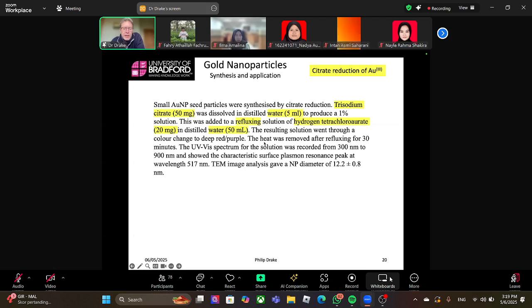You keep refluxing it. You then look at the UV vis spectrum, record from 300 to 900 nanometers, and you should see the surface plasmon resonance peak, 517. We're going to come back to the SPR peak later. It's a very important measurement. So the UV vis spectrum of a gold solution should have an SPR peak. Here we see the peak around 517 nanometers. And again, as a trained chemist, from that peak, you get a very easy estimate of the nanoparticle size.